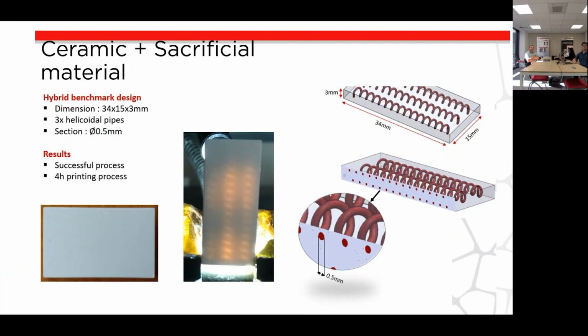Next. A few examples of what's been done. So that's been done on a C900 machine. The idea of this was to make a helicoidal design with sacrificial material inside an alumina block. So you can see on the right-hand side of the screen, the red helicoidal, those have been made with sacrificial material. And then with a section of 0.5 millimeters, so 500 microns, that got debinded and sintered. And you can see through the light that the sacrificial has gone away. So you get the helicoidal void inside the part. This is not feasible with normal SLA because obviously the cavity is closed, so you need to remove the sacrificial during the thermal process.